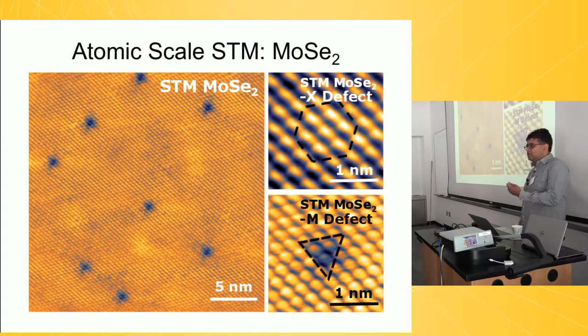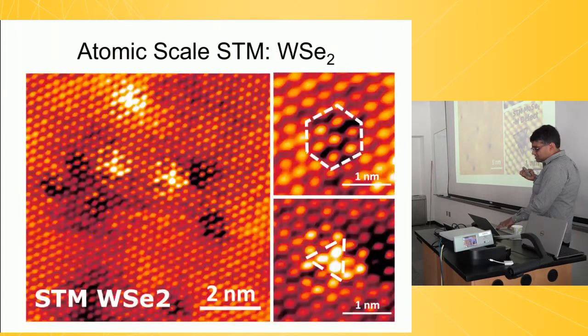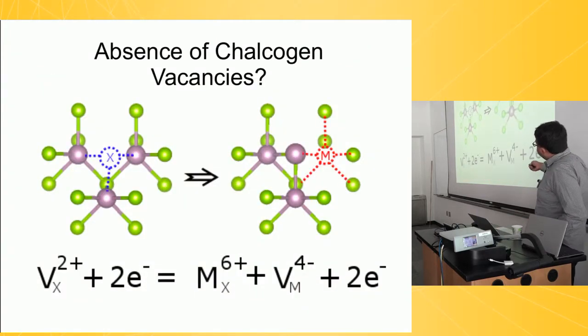What we believe is that during growth, you can have a metal atom pop in instead of the chalcogen. Once the metal atom pops in, it's fairly happy to be there. We worked with our ab initio theory collaborators, where we said that during growth, you can have a chalcogen vacancy. This chalcogen vacancy is sometimes, on occasion, filled up by a metal atom. That metal atom could come from a neighboring metal atom, or from a metal atom in the melt. If it comes from a neighboring metal atom, you now have a metal vacancy, and it's quite easy for that metal vacancy to drift away. So what you're left with is this anti-site. Once this anti-site is formed, it's reasonably happy to stay in this material. It's not too bad. That's our picture for what the anti-site is.